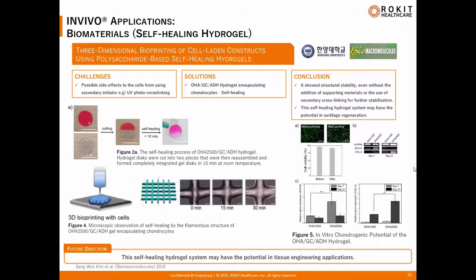A great thing about this hydrogel is that it forms bonds instantaneously without post-gelation or additional cross-linking processes. After you cut these into pieces, as you can see here, the pink and the white, the two colored discs made this self-healing hydrogel reassemble and integrate completely in less than 10 minutes at room temperature. It supported not only viability, but functionality of chondrocytes expressing SOX9, as seen here in the gene expression. Going forward, the group believes that this self-healing hydrogel has potential in cartilage, as well as various tissue engineering applications, and even in time-dependent drug delivery systems.